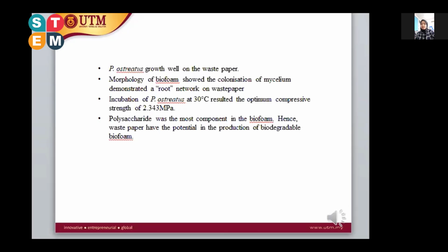So for the conclusion, this project is actually a preliminary study that varied three types of fungus grown on waste paper as a substrate for biofoam production. From this preliminary study, PO, which is Pleurotus ostreatus, resulted in the highest colonized area on the waste paper compared to the other two types of fungus and has potential for biofoam production. Besides, the results demonstrated the visual appearance, density, and also physical properties of biofoam that are influenced by varying temperature, spawn weight, and also moisture content.